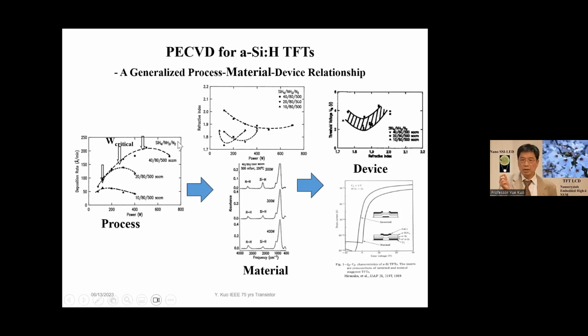But people neglect one thing. During dissociation of the molecules, hydrogen is generated. Hydrogen is important to passivate dangling bonds in, for example, the gate dielectric. However, when hydrogen is at high concentration, at high power, with high ion bombardment energy, it becomes etching. It can damage the surface, can remove the passivation hydrogen, and cause dangling bond formation. There's a reverse of the refractive index and it causes the threshold voltage to increase. So this is the etching-deposition phenomenon that can be used to explain the whole process condition to the device.